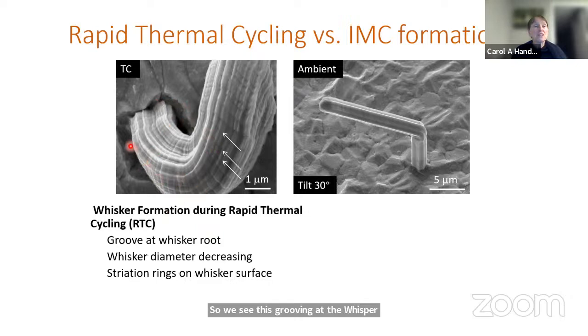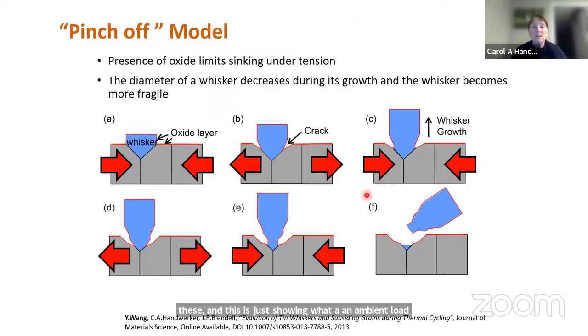We see the whisker diameter decreasing. We see striation rings on the whisker surface, sort of like tree rings, that each thermal cycling corresponds to one of these. And this is just showing what an ambient one looks like due to intermetallic growth. So what we found was that we actually get pinch off of the grains. And so you can see what the effects of compressive and tensile stresses are.